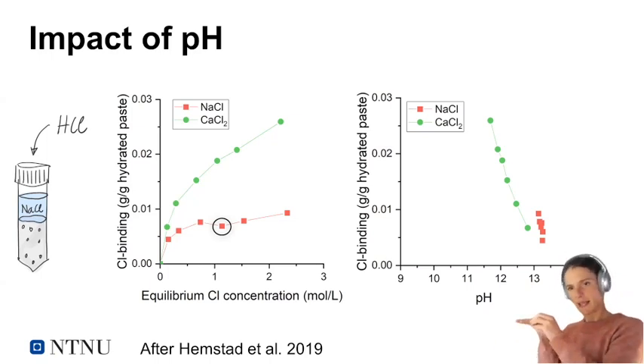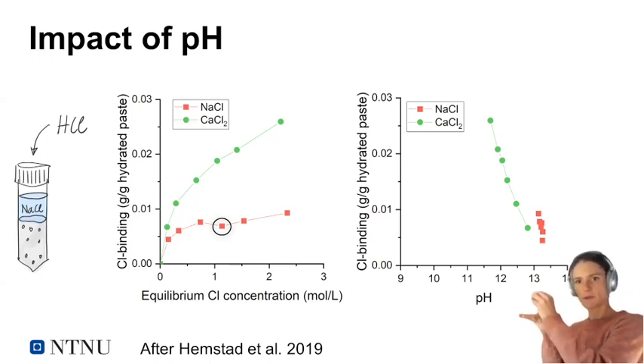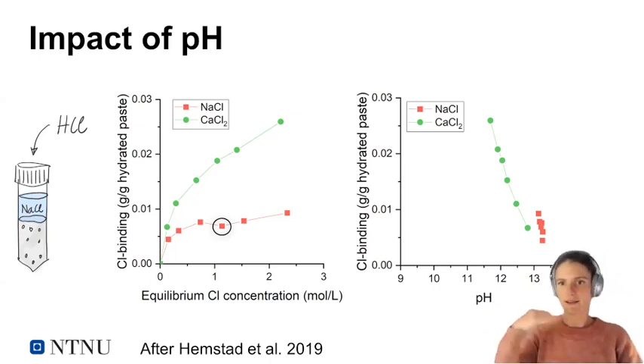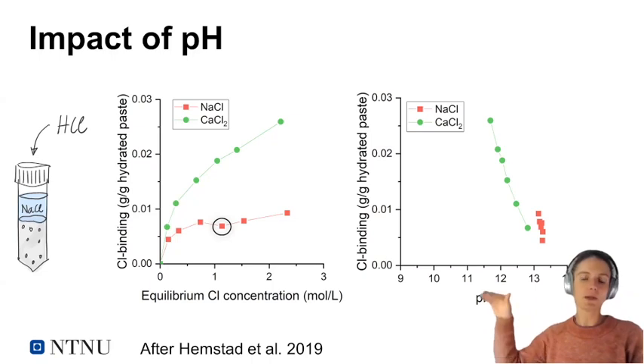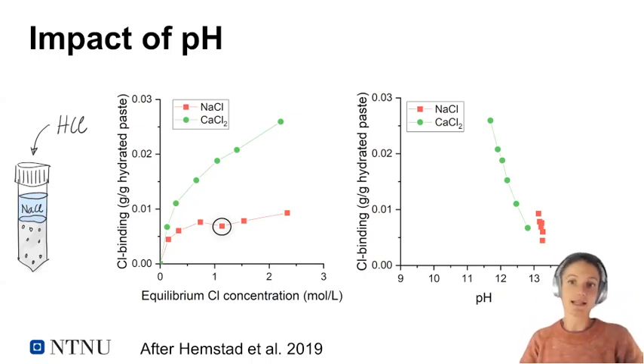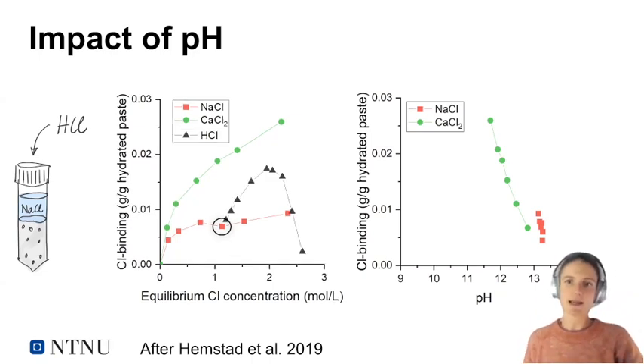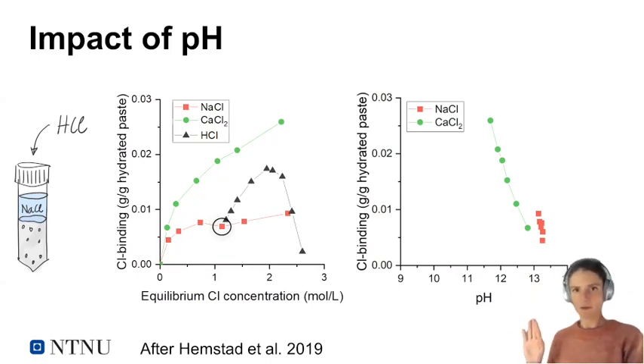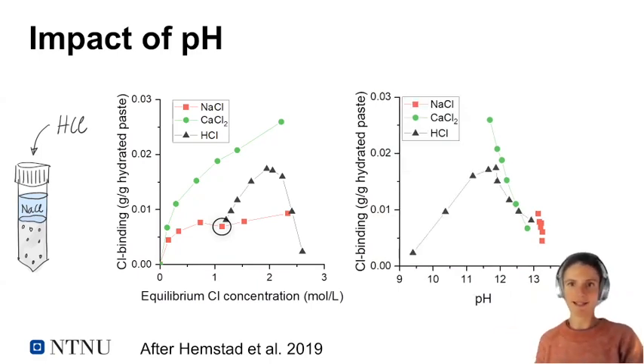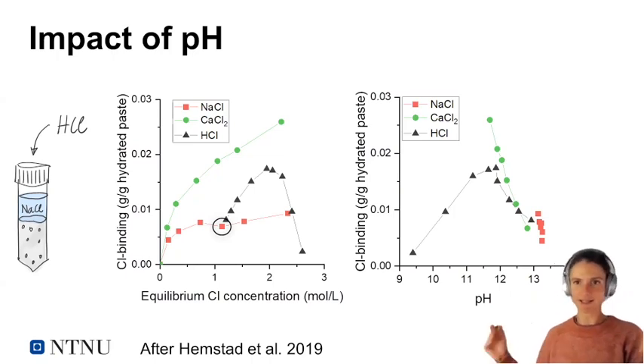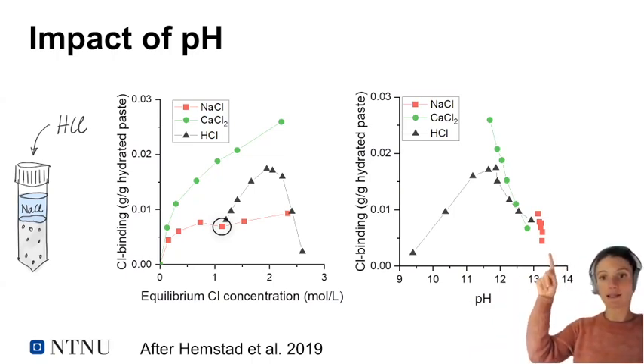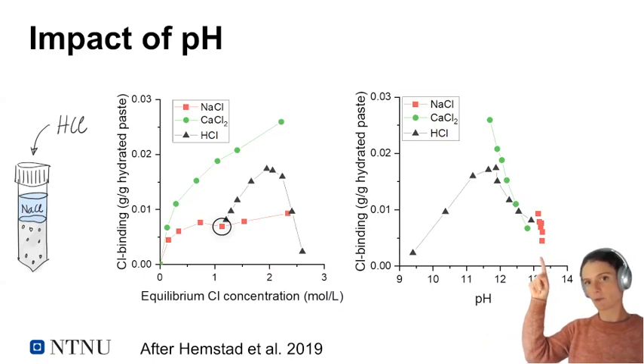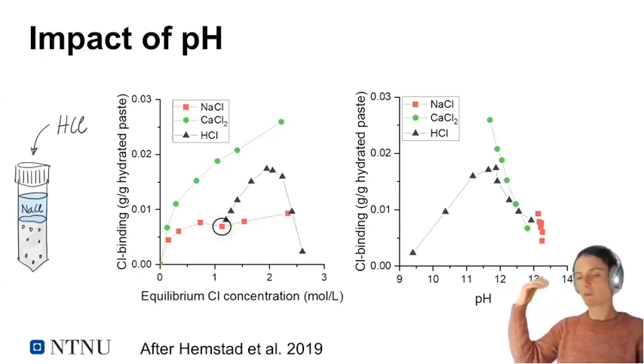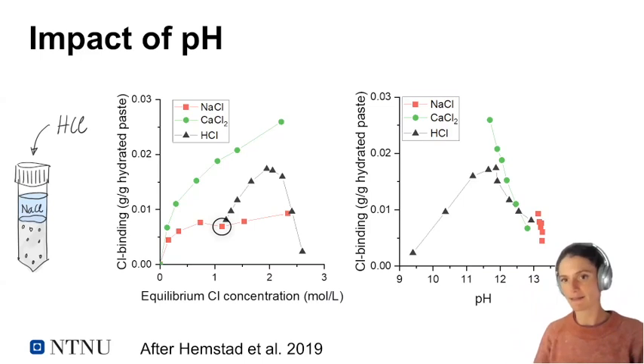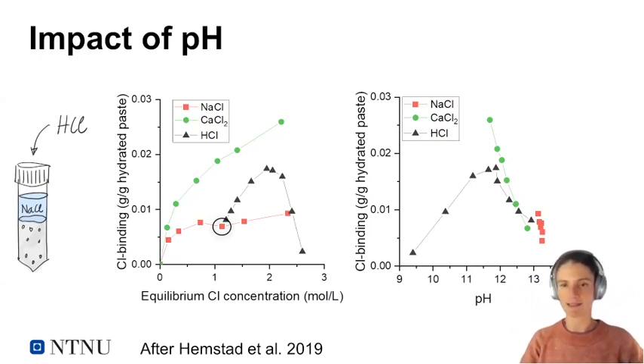And our idea was, if we're changing the pH, should we move closer towards the calcium chloride curve? And how far would that go? And would we at a certain point have, again, a decrease in binding? And that's exactly what we observed. When we are decreasing the pH by adding hydrochloric acid, we are first increasing the binding to a certain point, and then when we surpass a certain limit of pH, we're then again decreasing the chloride binding in our paste.